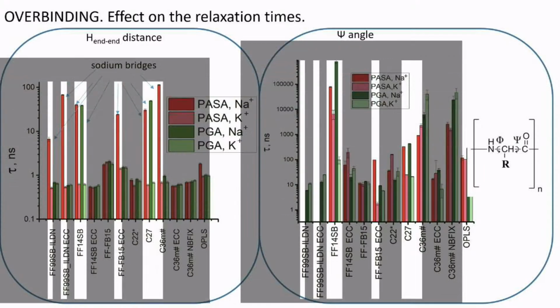Here are the systems with the sodium bridges. Also we checked the relaxation time of the dihedral angle of the chain backbone, and it is interesting that in this case the effect of sodium bridges is more unpredictable. Of course, in most cases, the system with sodium has more relaxation time because of the sodium bridge.